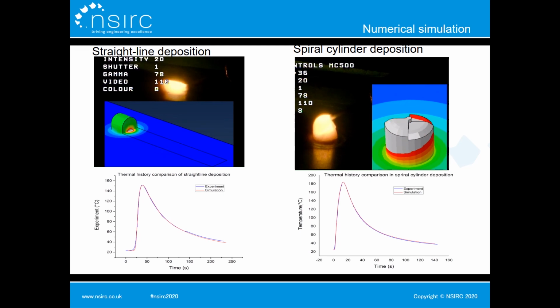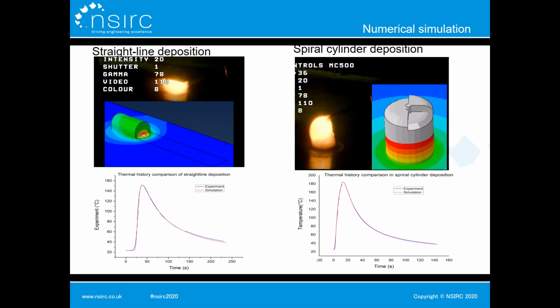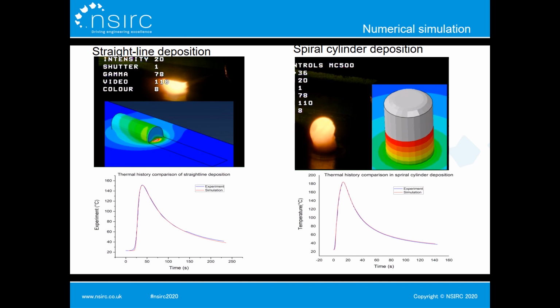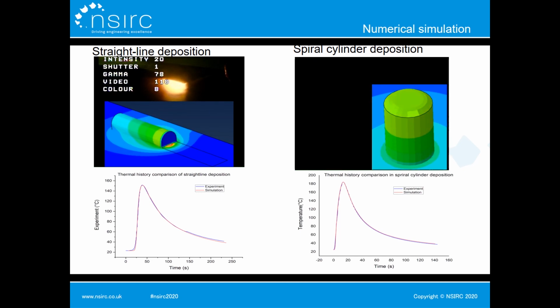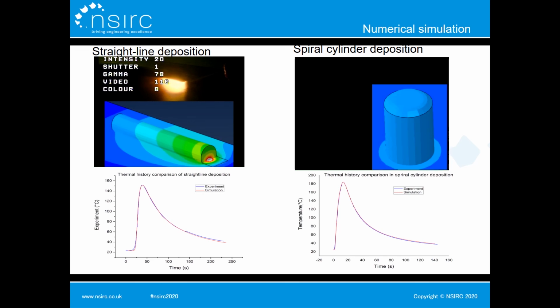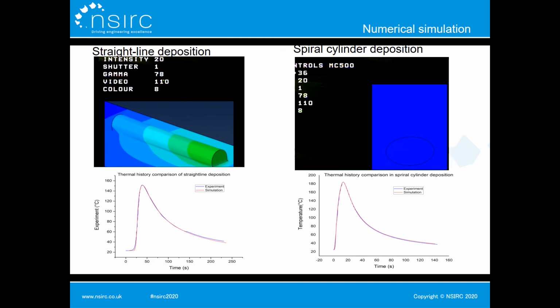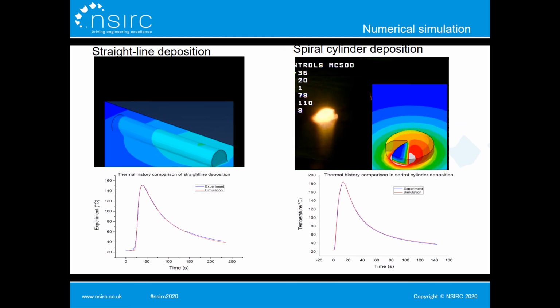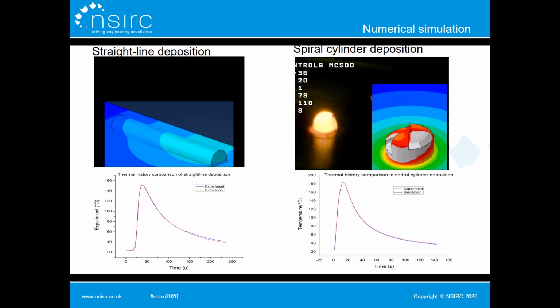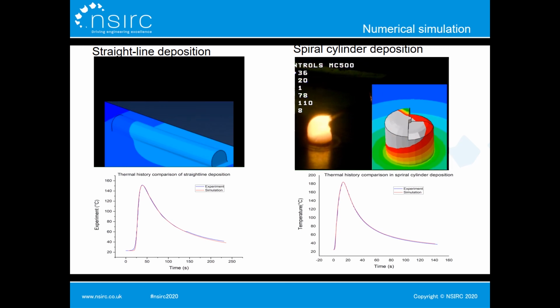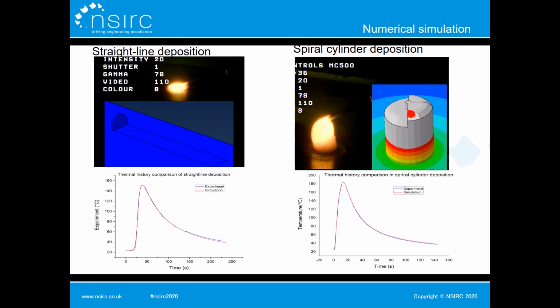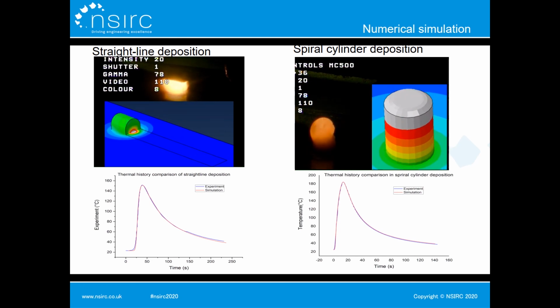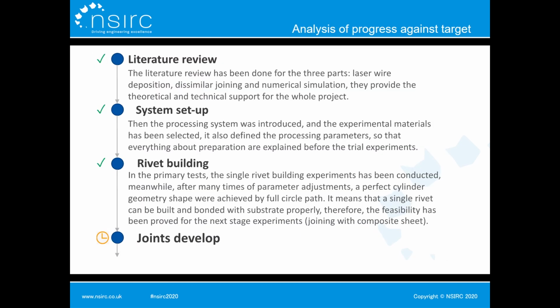Graphs below are the temperature data comparison. The thermocouple's position is at the bottom of the substrate. The blue line is the experimental result and the red line is the numerical modeling data. They show a high agreement in the thermal history, so it means that this modeling has certain reliability in temperature field simulation and prediction. Based on it, in future work, a residual stress model will be developed to analyze the parameter influence on it. So above is all the work I have done in my first year.